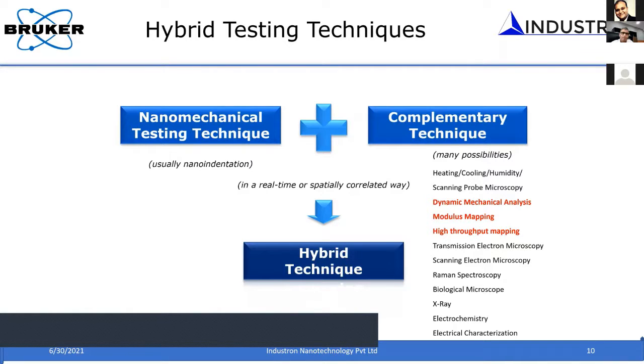There are other things that you can do with this transducer. For example, instead of applying a force quasi-statically, you can also apply force dynamically. What I mean is that you can apply an oscillatory force and then measure the response. We call it DMA. So in that way, you can have hybrid techniques in combination with this standard quasi-static nanoindentation technique to develop a further understanding of the stresses and strain that is being induced, or, when you put a stress and strain onto the sample, how the sample is going to react. We can all do that, okay?